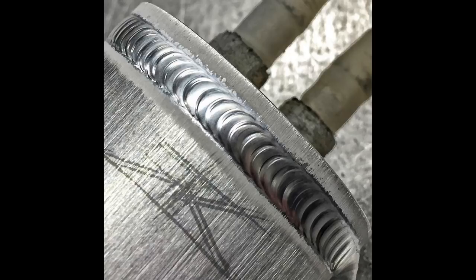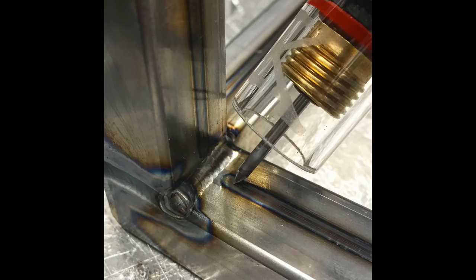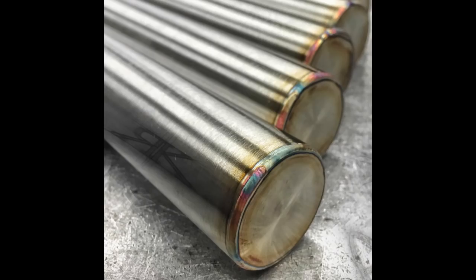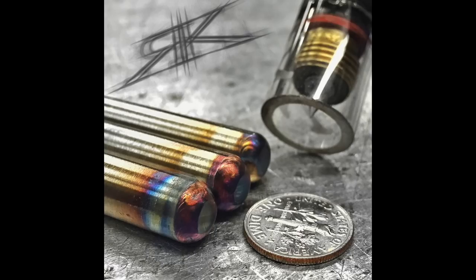There was an Inconel 718 casting test, Inconel being a nickel-based alloy, that recommended 5% hydrogen. And actually it helped a lot, because what the hydrogen does is it actually burns, and so any remainder of oxygen that's in that arc plume will burn up, basically, and so it provides a reducing atmosphere there. And it just wets out a little bit better, and man, just that little bit sometimes makes you able to wet out with less amperage.